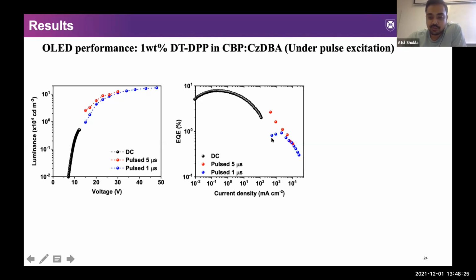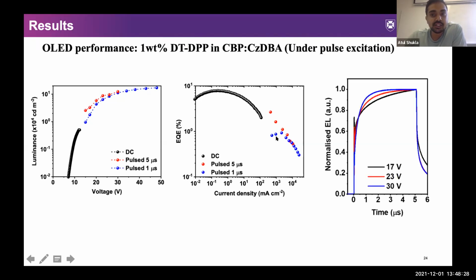And the reason for this is the early saturation of the transient ELs, which is mainly because of the quenching of triplet excitons itself due to TTA and TPA. In these systems, there's an additional loss mechanism, that is Dexter energy transfer to DPP. So all of these losses are expected to increase.